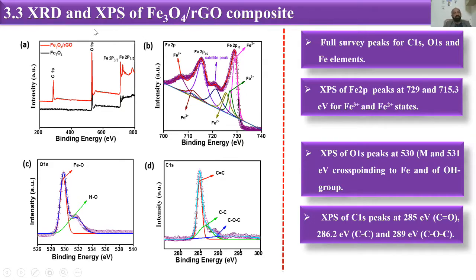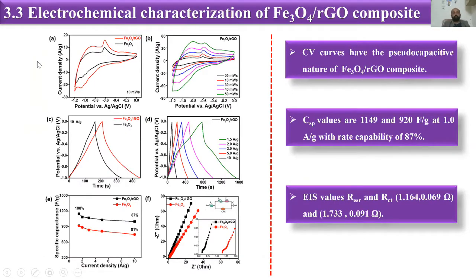Then we have done their electrochemical characterization. Again, we have done the CV curves for our system, and they have shown the pseudocapacitive nature of our system. Then we have done GCD curves, and again we have got good specific capacitance for our Fe3O4 RGO composite: 1149 and 920 F/g at a current density of 1, with a rate capability of 87%. Then we have calculated the specific capacitance of our composite and our iron oxide material, and then we have calculated their EIS spectra, and we have got the RCT and ESR values for our system.